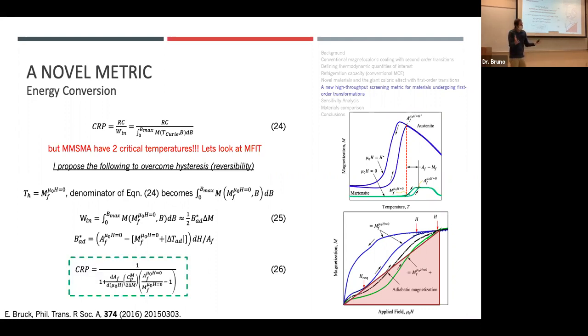Crunching this all down into this metric, coefficient of refrigeration performance, it is unitless, I find I can actually quantify this by just 5 basic parameters that are highly reported in the literature. That's the transformation temperatures in zero field, the heat capacity of martensite, so both of those can be obtained with simple calorimetry measurements, the magnetization change across the transition, and the Clausius-Clapeyron slope. So I need thermomagnetic response, and I need calorimetry.